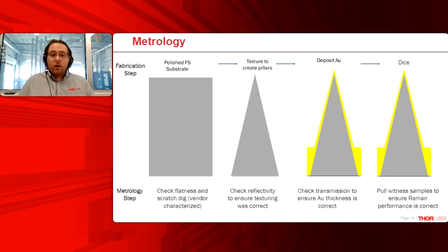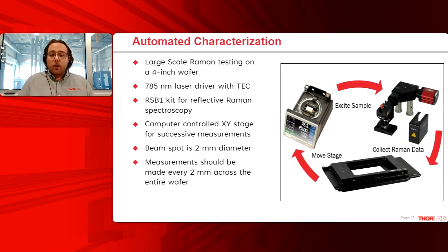So you might be wondering, how do we measure all of these characteristics across an entire wafer? Well, we have developed an automated characterization setup. In this case, we use a 785 nanometer laser driver. We use our RSB1 kit for reflective Raman spectroscopy, and we use a computer-controlled XY stage for these successive measurements. These all talk together in LabVIEW programs, and we can use this to place an entire 4-inch wafer into the setup and successively measure point by point across that entire wafer to ensure that we get a uniform response.